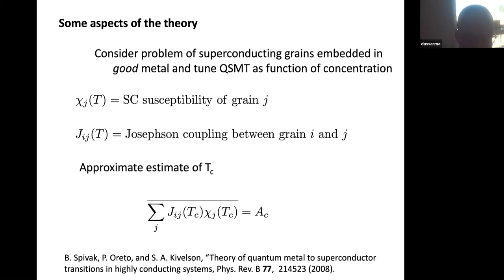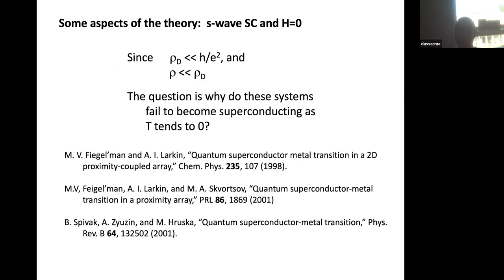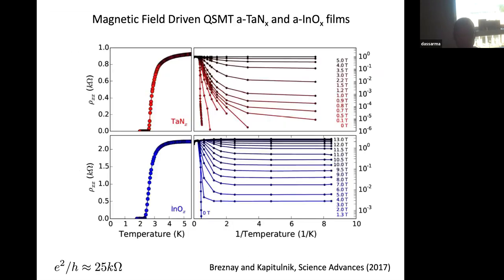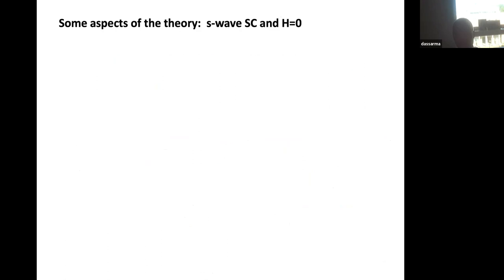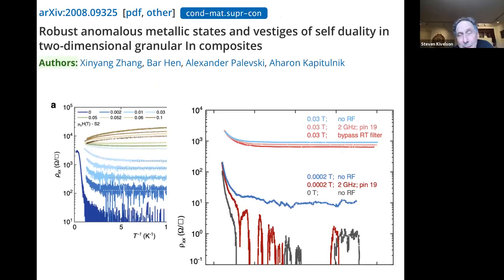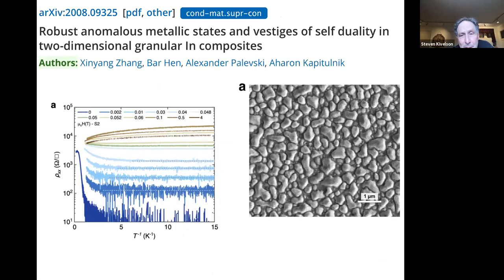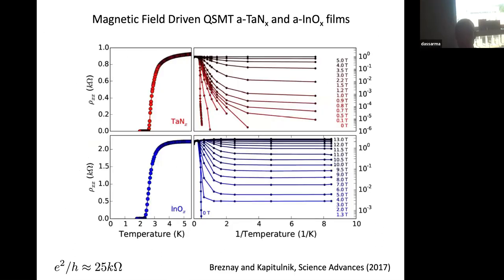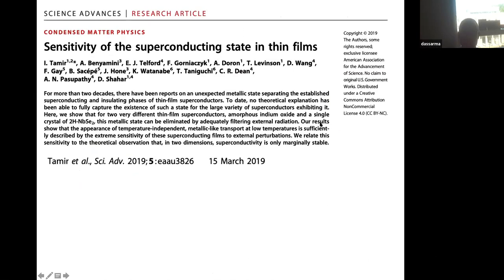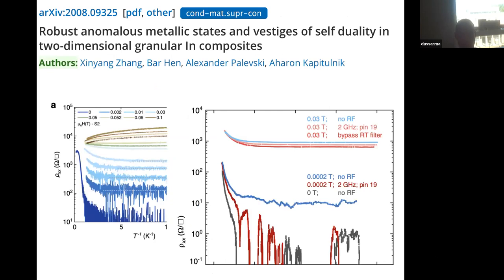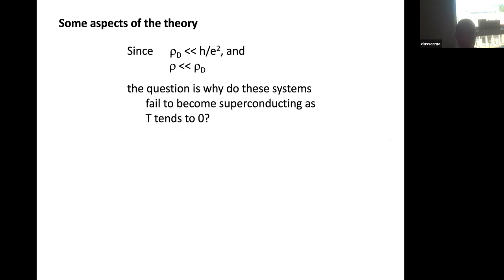Because you showed results only on an exponential log scale where you cannot see anything. This absolutely flat region that you are showing is really flat, meaning if I now do a standard weak localization fitting, it doesn't work at all. Correct. For one thing, it's got the wrong temperature dependence. To the extent that it's temperature dependent, it's more metallic than insulating, right? Yes, the resistance is always decreasing with decreasing temperature. So the answer is that, to the extent experimentally one can establish, they remain metallic, with no sign of weak localization.